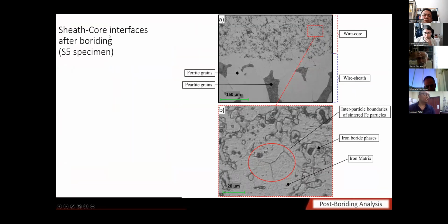And here is the sheath core interface. It is very continuous. These grains are ferrite and pearlite grains, because the wires are subjected to elevated temperature and rearrangement of the grains occurs there. They are coarse grains. And here is a region,